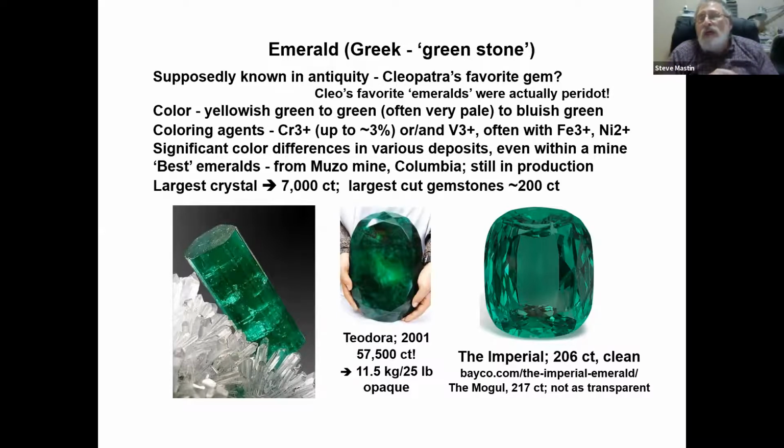And that's why those defects, the inclusions, can become important, because it's actually very easy to tell the difference between an emerald and a peridot by looking at it through a loupe. Emeralds are the exception to the beryl family. They almost always are included. They have defects in them, not cracks and things like that. That's bad. But they usually have so many inclusions in them that the inclusions have a name. It's called jardin, the garden. And you expect to see that in a natural emerald.